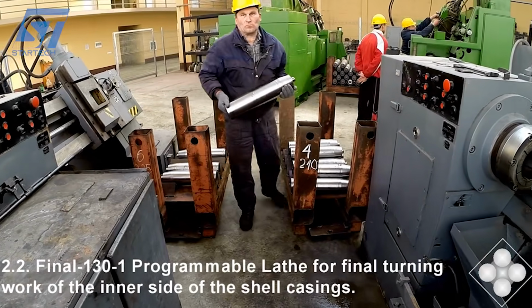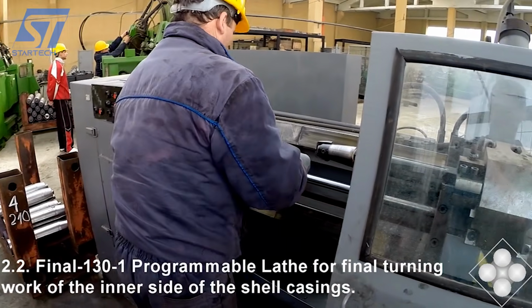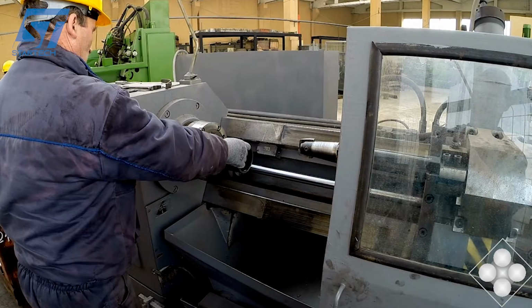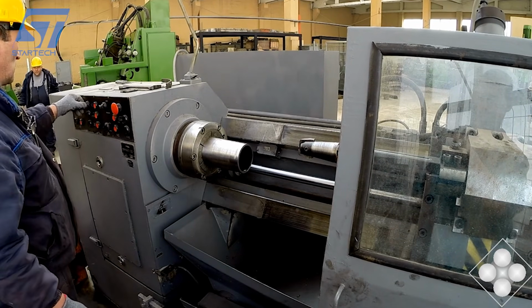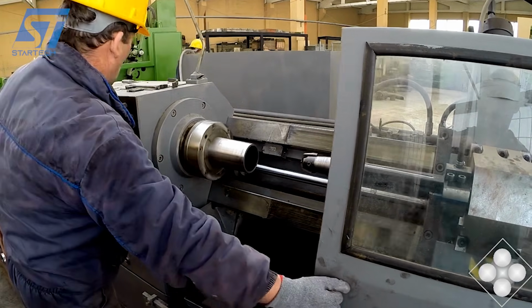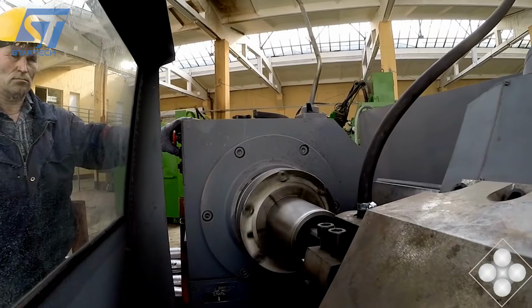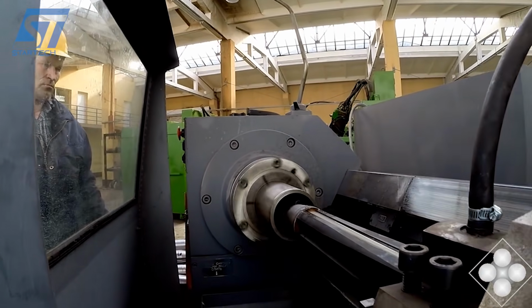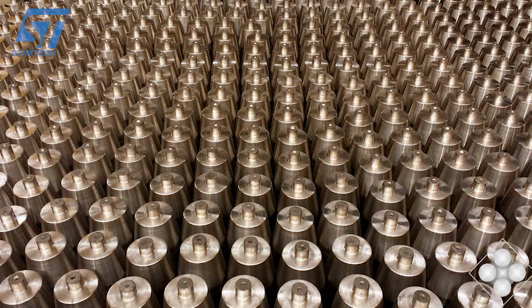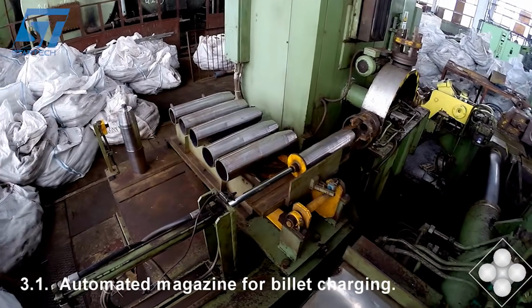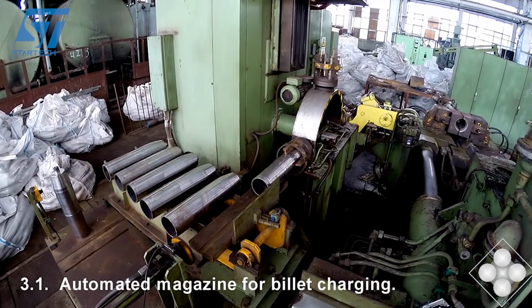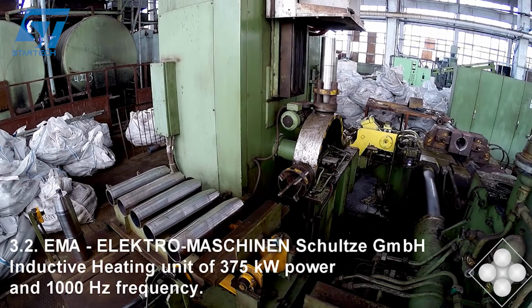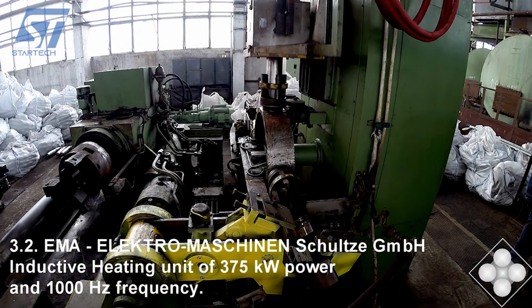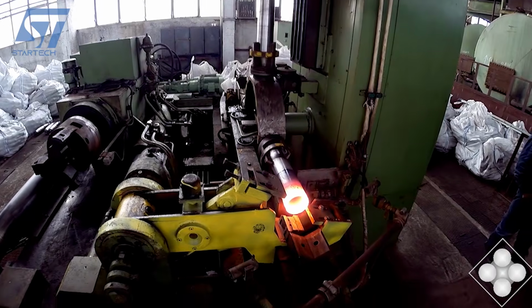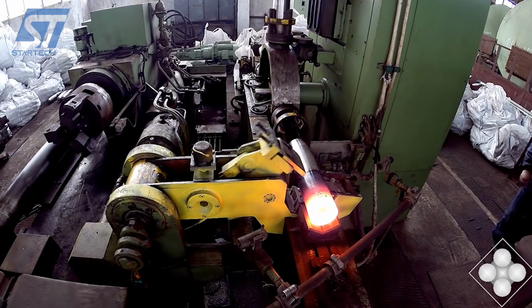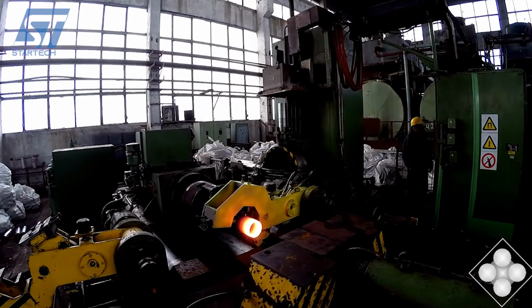In a typical forging cycle, a billet preheated in an induction furnace to between 1,100 and 1,250 degrees Celsius is placed in the bottom die. The operator triggers the stroke. In a fraction of a second, the ram descends with forces ranging from 1,600 to over 10,000 metric tons, depending on press size, and the metal flows and fills the die cavity with a satisfying thunderous crash. Flash, excess metal squeezed out at the parting line, is trimmed in a follow-on operation.